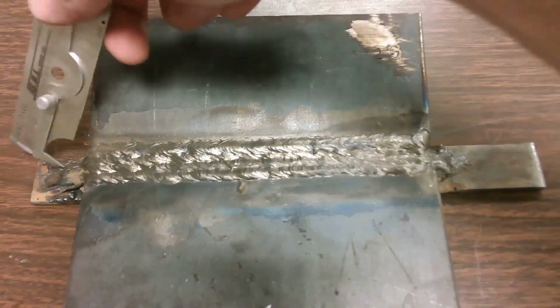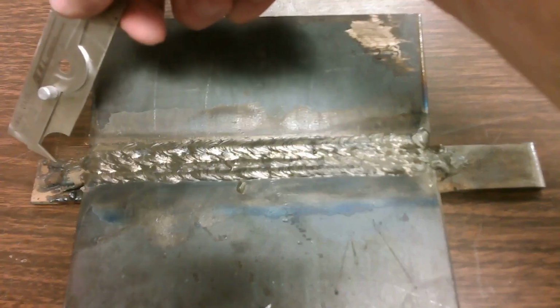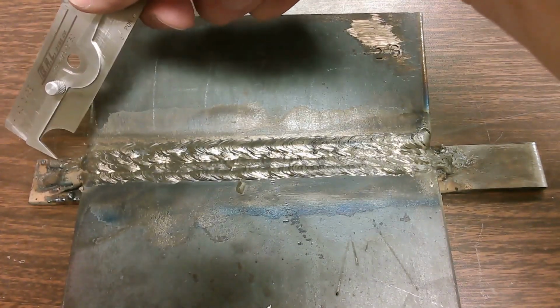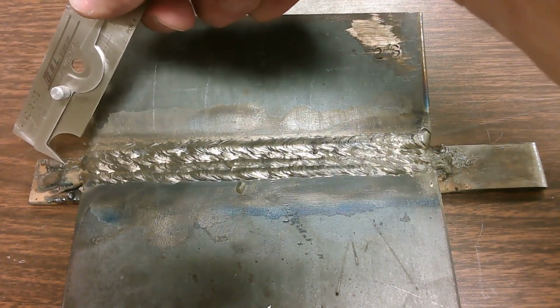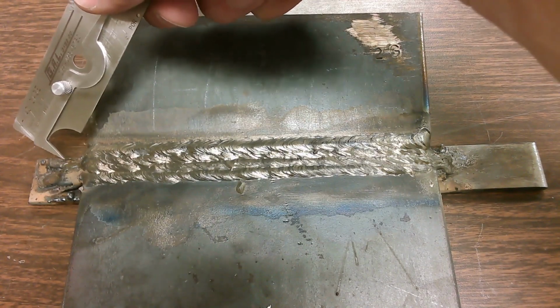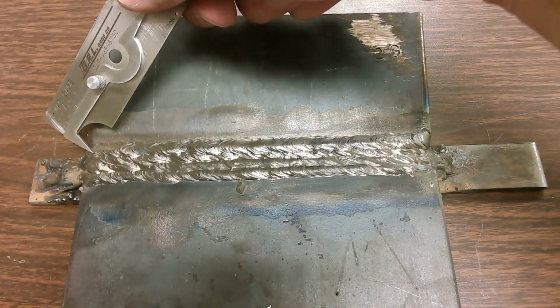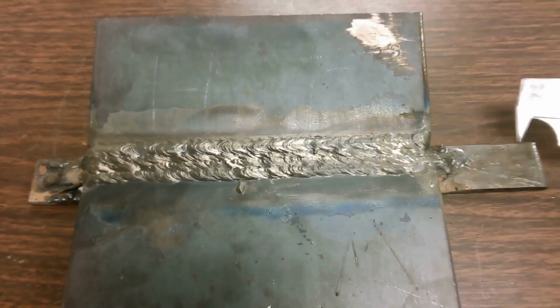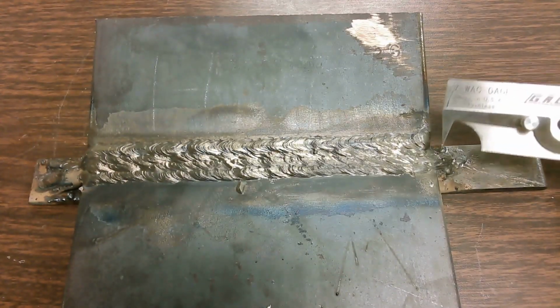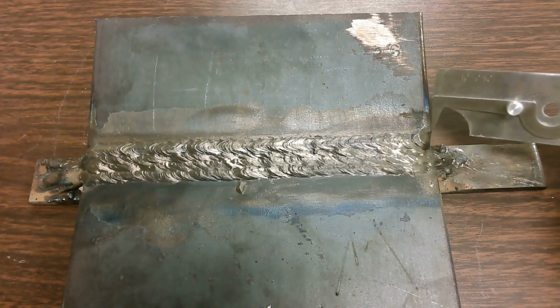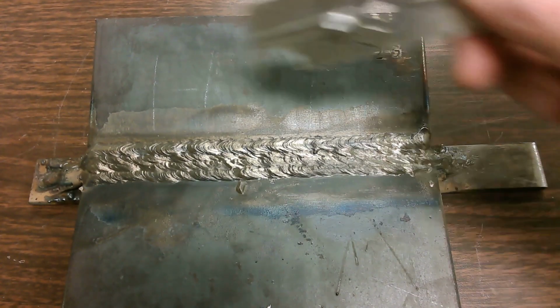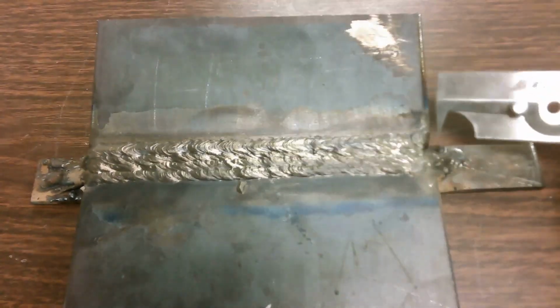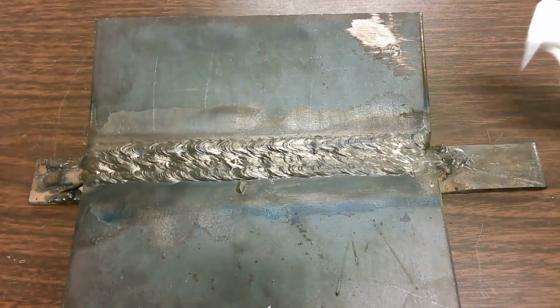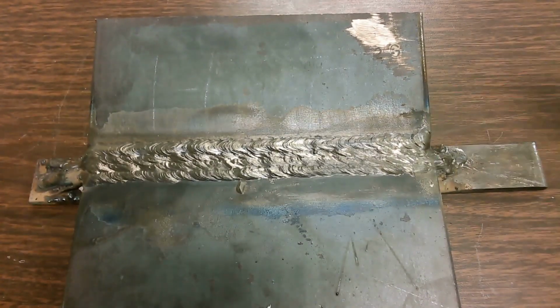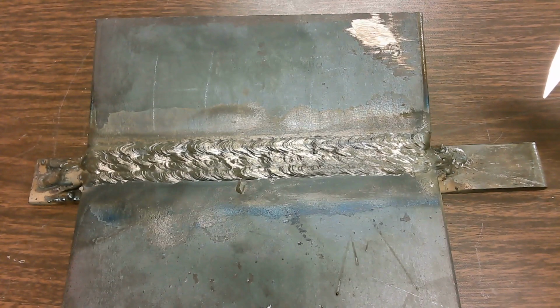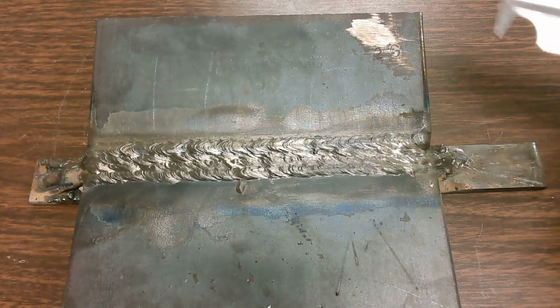Notice the backing strip on these. Okay, I like to see them weld out onto the backing strip at the beginning. It helps heat things up a little bit, helps get that plate warmed up so that you don't have a cold weld when you're first starting. Same thing, finish out onto that backing strip, allowing you to make that weld to the end. You're always going to get a little melt back on the edges. I don't check anything within about 1/2 an inch of the edge. You're going to get that, and that's not a big deal. So overall, this looks like a pretty decent weld.